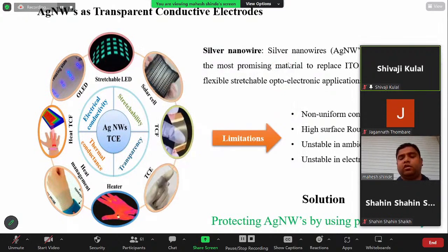To solve this problem, we need to provide a passivation layer to the silver nanowire based transparent conductive electrode. Many works have been reported to protect the silver nanowire, such as PEDOT-PSS, reduced graphene oxide, CNT, and metal oxide. But most of these passivation layers are only effective for a short duration. So we need a proper passivation layer to protect the silver nanowire for use in the TCE for many applications.